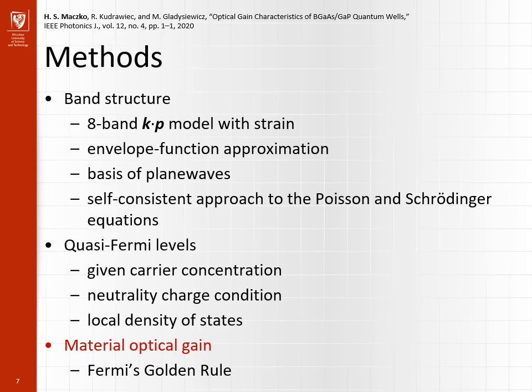Quasi-Fermi levels are calculated based on neutrality charge condition with two-dimensional carrier density taken as a parameter. Local densities of states are calculated to determine quasi-Fermi levels in each step of the predictor-corrector method of solving Poisson and Schrödinger equations. Material optical gain is calculated within the standard approach based on Fermi's golden rule.